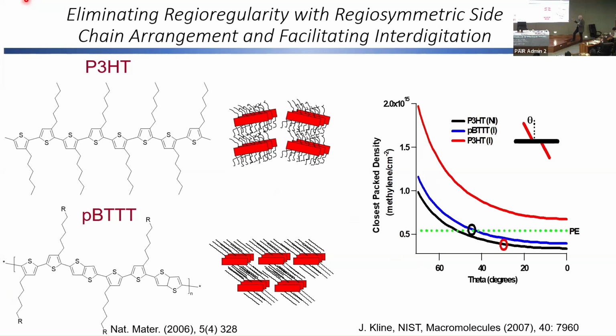That's one thing. But what we also notice is that if you model this polymer and you interdigitate side chains, so in other words, if there's another P3HT just above and you bring it together, no matter what angle you project this side chain from the main chain, at every single angle, you can see we've got a very high close packed density. Even at 0 angle, that's the minimum, right, when it's completely orthogonal. And that number of the close packed density in methylenes per centimeter squared is greater than crystalline polyethylene. So that's not physically possible. Linear crystalline polyethylene has the highest possible packed density for an alkyl chain. So for this to be above that, it's not physically possible.